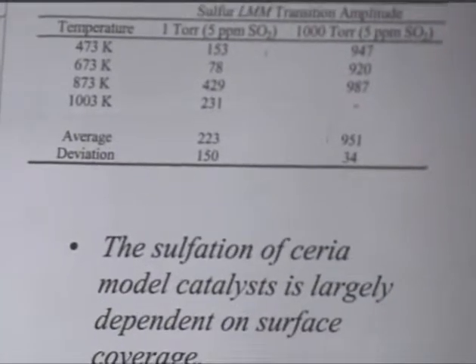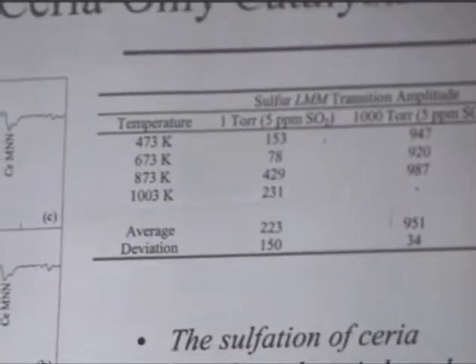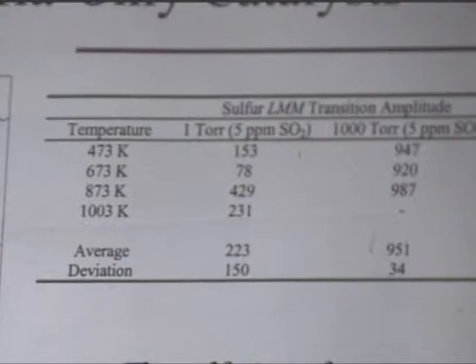Now, we'd like to point out this says nothing about the state of the surface species on there. We're pretty sure that we see some changes, sulfate, sulfite, and different things as a function of temperature, but we're still investigating that. For the lower pressure, we think this corresponds to about 0.15 to 0.2 of a monolayer, and some of what we're seeing in this variation we're sure is due to the fact that no matter how careful you are, in a pressed powder you're going to have voids in places where SO2 can react and adsorb. If you look at these, there's no necessary trend, but you do see some variation. But in general, what we find is we didn't see big differences in just the raw amount of sulfur as a function of temperature, but we certainly did as a function of coverage as reflected by these different pressure measurements.